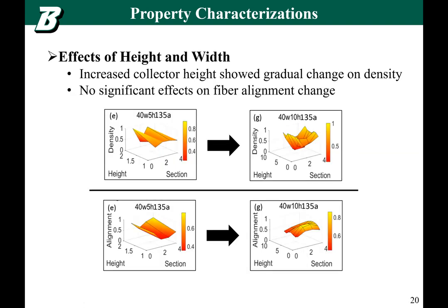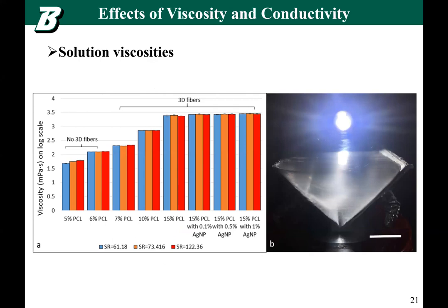So we also did a MATLAB plot of every fiber density and alignment point, to see if there's a significant change when we are changing the collector height and width. And we found out that increased collector height showed a gradual change in fiber density, but there's no significant effect on fiber alignment change. So we investigated the effect of collector geometry, and we found out that the peripheral area always has more fibers compared to